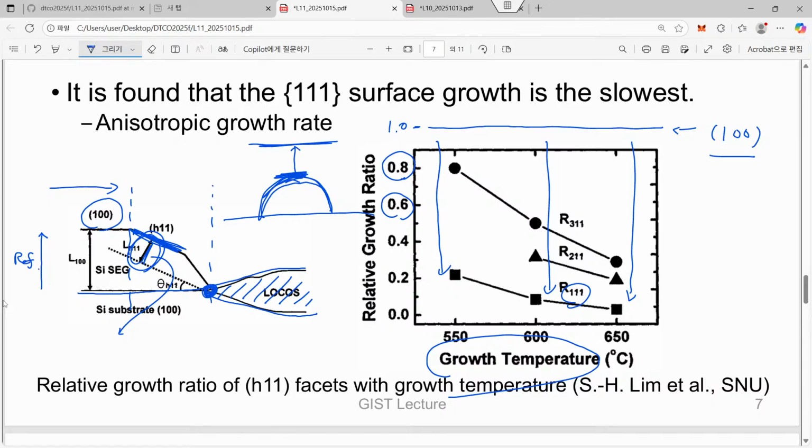And let's say that for this 45 degree, let's assume that we have a very slow growth rate. So instead of this large amount, let's say that it goes only in this way. And in between, we assume a moderate or smooth interpolation. Then what will happen? Although it was a circular shape at the beginning, later we will find that the shape looks like this, because this part is slow, and this slow surface later